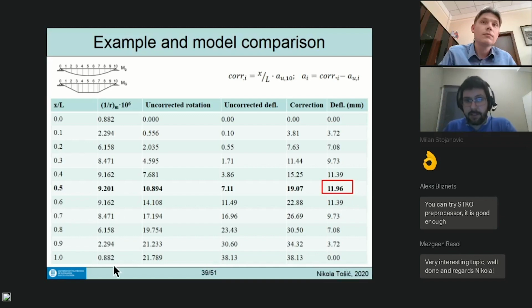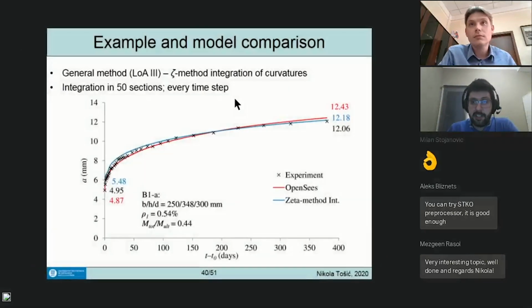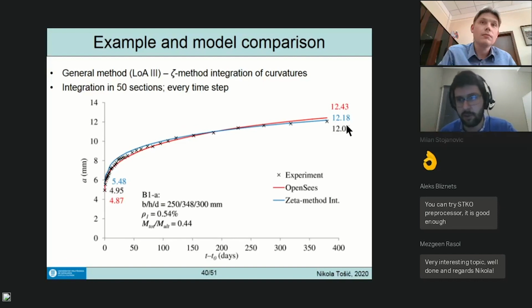And that's it for that. If I do it in 50 sections, like I did here, and I do it for every time step, I get a bit higher, 12.18. So I have an increase of like 2-3%. So, going from 10 to 50 sections, it's not going to bring you more than 5%, at least in this case. And these are the results.